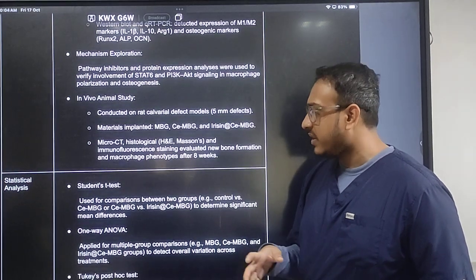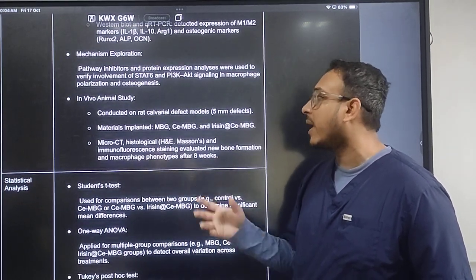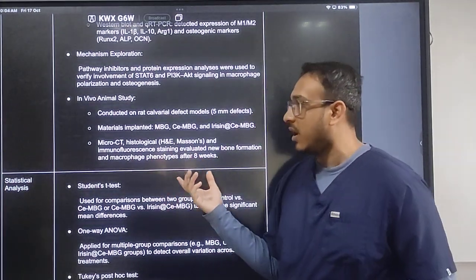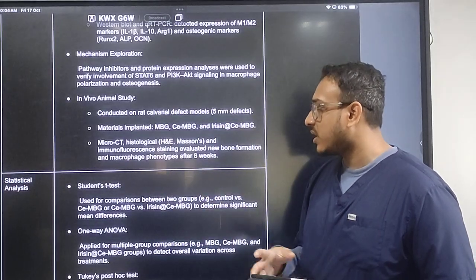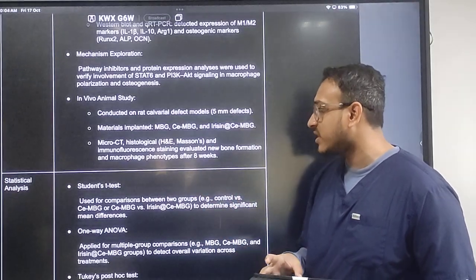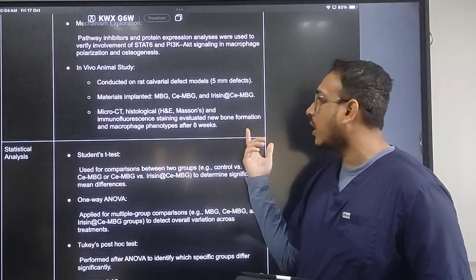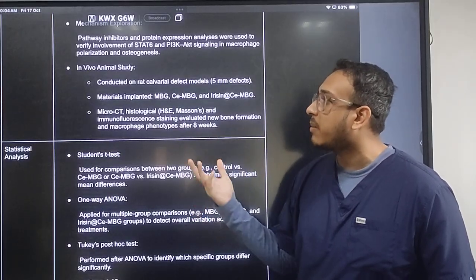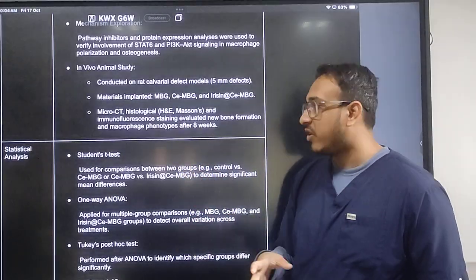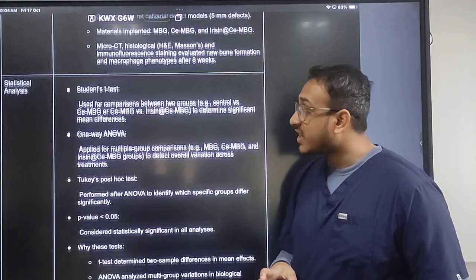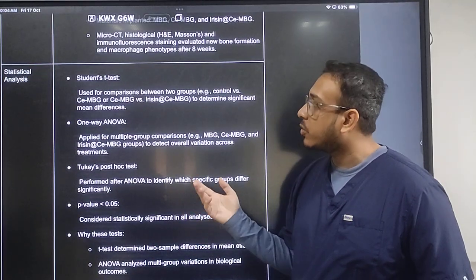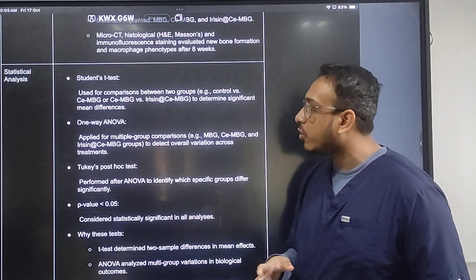defects. They implanted the material, followed by examination by micro-CT, histological staining and immunofluorescence staining. They evaluated how much new bone was formed and the macrophage phenotypes after 8 weeks. For statistical analysis, they used the Student's t-test for comparison between two groups,